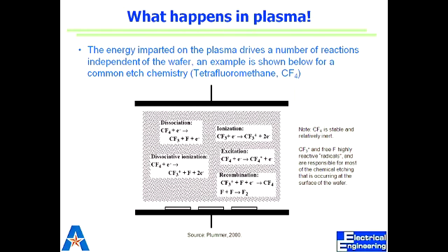Degree of ionization. Degree of ionization, that is how reactive the gas is. Anything else? Pressure, temperature. Yes, temperature. So temperature can change, pressure can change. Pressure means that the higher the pressure, the higher the etch rate, because in that case you are providing more and more etchant. The number of etchants is increasing.